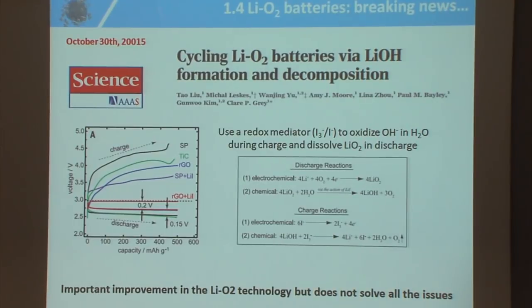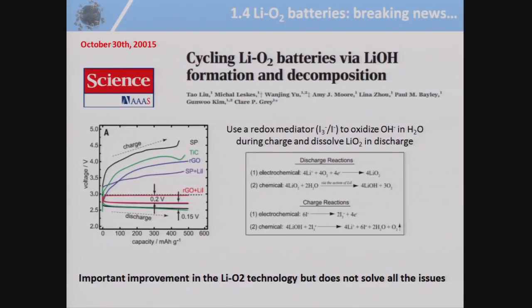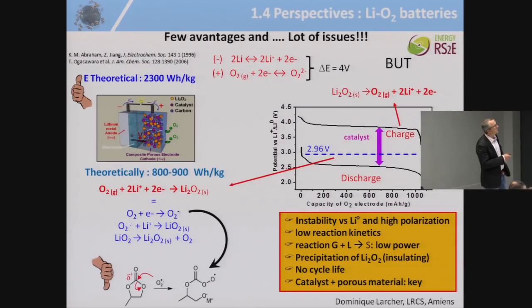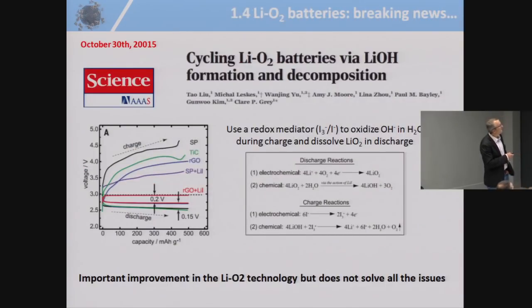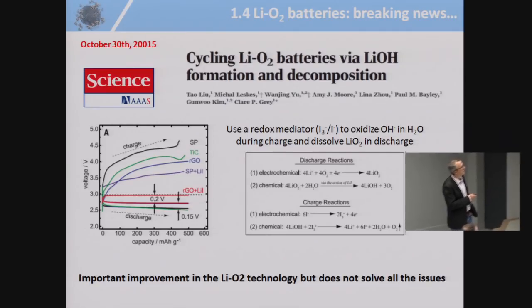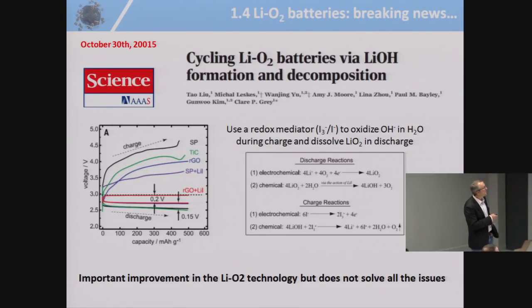However, last week, so it was October 30th, 2015 in Science, the group from Clare Grey at Cambridge University in UK, they have published a very interesting paper. It does not solve everything, but this is the beginning of the answer. You remember what I show you here. This is the discharge and this is the charge, huge polarization. You see, they use graphene oxide as an active material, and this is the discharge, and this is the charge. Polarization is only 0.2 volt. So they have solved a part of the problem.